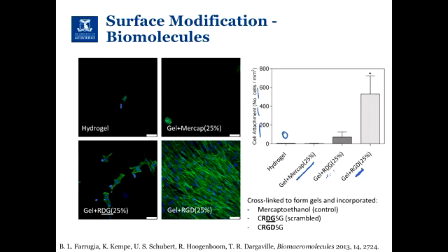You put the RGD sequence in there, cells love it. So you can go from a material here, proteins don't like to adhere to it, cells don't like to adhere to it either. You keep the hydrogel material the same, you put in the sequence RGD that cells like to bind to, and cells all of a sudden love a material. So it's just an example of how you can change the properties without changing the chemical properties of your bulk material, change something small to another part of the material, and change completely how biology behaves towards it.